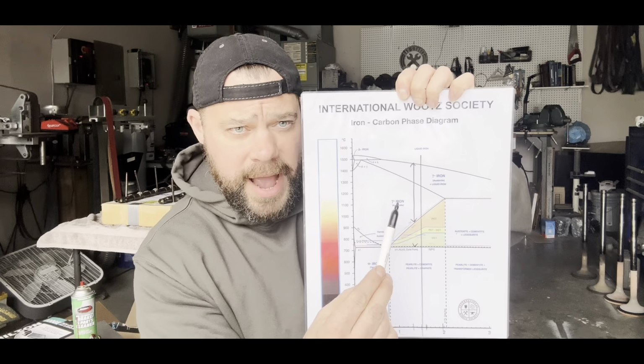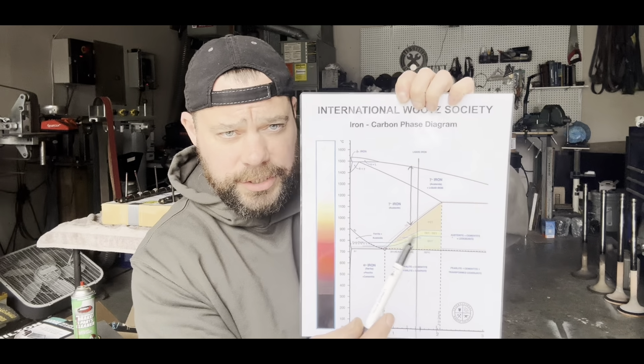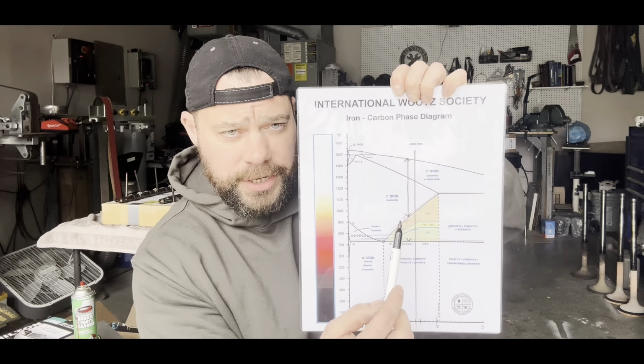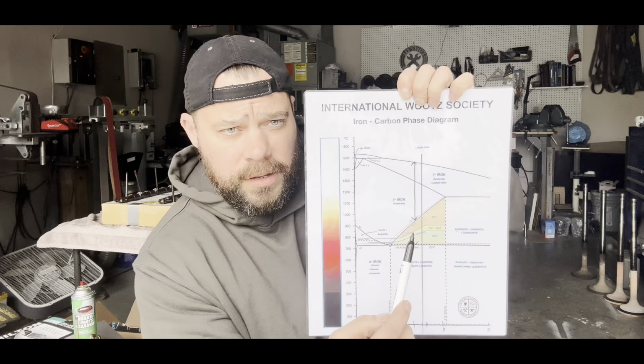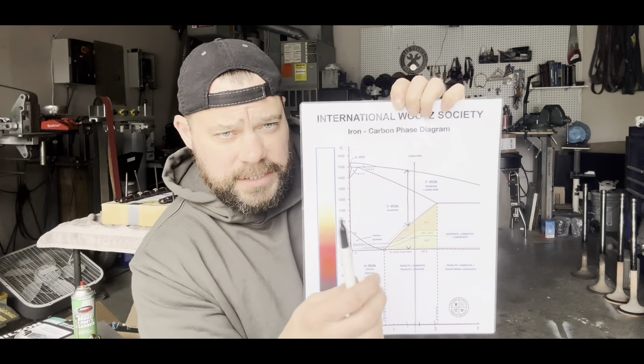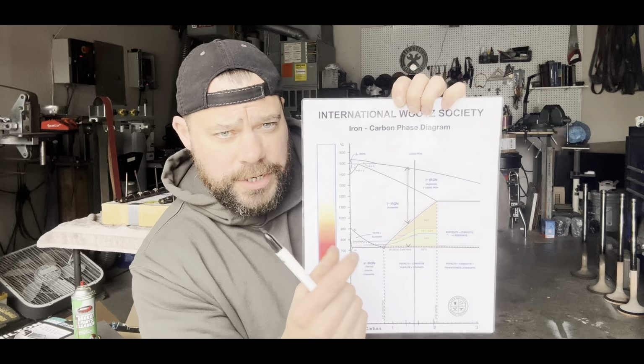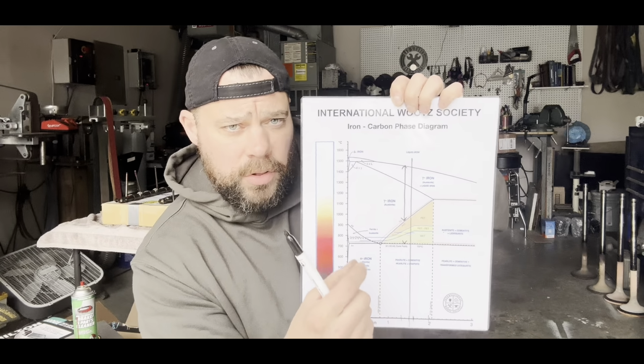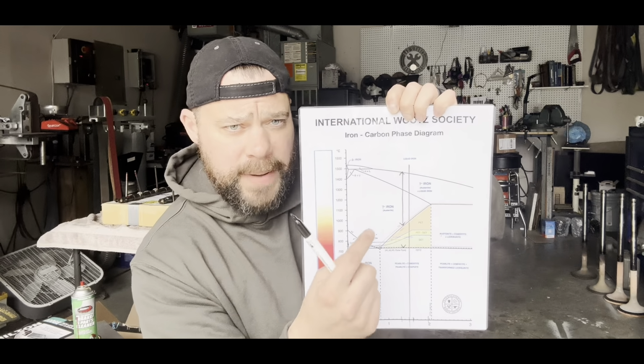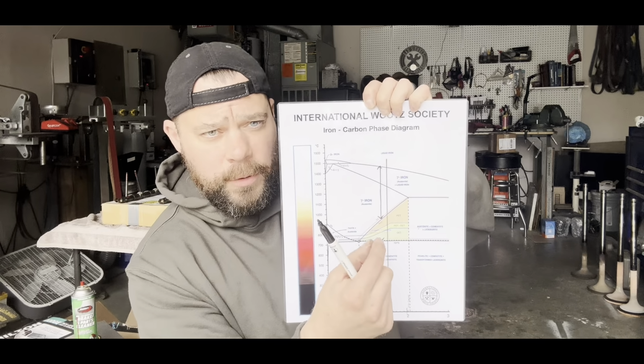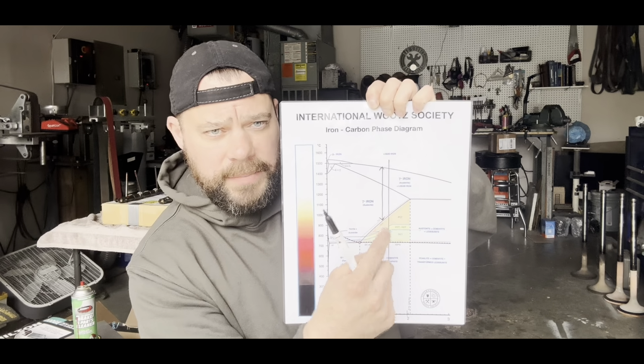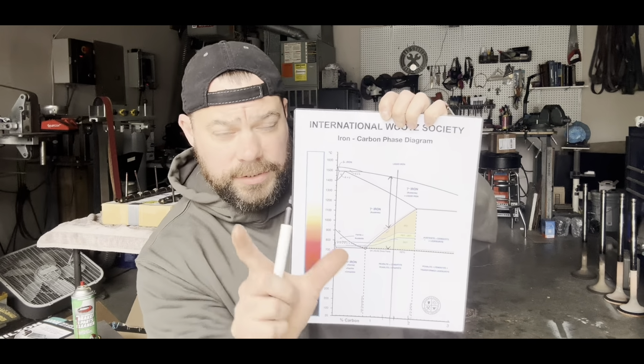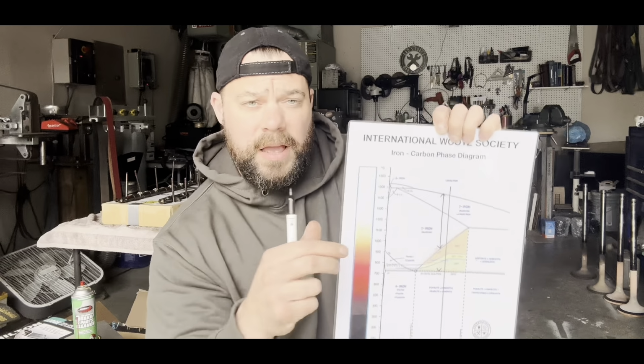And as you come down even below ACM, there's still carbon migration happening. You're still having carbon precipitate inside the grains, and that's where you see those needle-like carbides. They're no longer going to precipitate on the grain boundary. They will precipitate inside the grain as needles. So that's why I look at the structures right away, because that tells me I'm in the right carbon range.